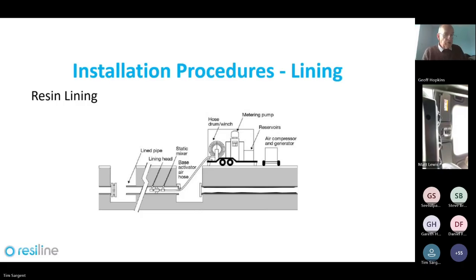So you will then start pumping material. You have a spin-up stabilization period in the open trench at the far end, and then basically you would start winching back the umbilical hose, which pulls the attached spray head with it, and you will then spray your coating centrifugally onto the pipe wall, and the pumping rate that you have combined with the rate of pullback gives you the lining thickness that you achieve. That's the sort of basic process.